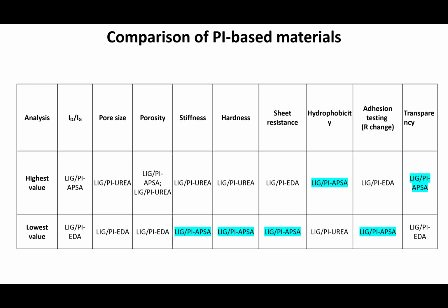Here we have a table such as this one, where we have most of the parameters that we studied, and then we put into the table which one of these materials has the highest value, for example, for stiffness, which one has the lowest value. And then you can, for example, observe this one. I selected just one to give you an example: this is the polyimide APSA sample with graphene on it. It has a very low stiffness and a very low hardness, so you can stretch it, and it's soft.